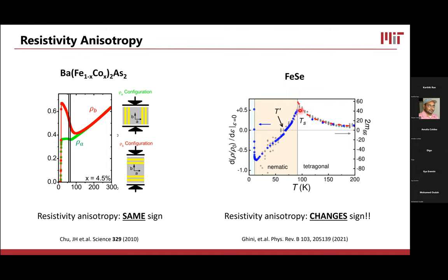But then it does something very strange once you cool below the nematic transition. It has an initial positive value, and then it decreases with cooling. And somewhere about halfway towards zero Kelvin, it actually flips sign. So it goes from having a positive value of the elastoresistivity to a negative value. This paper is from Coldea's group. And if they get very close to zero, they seem to see it flip sign again. I don't really know what's going on there, but it's a very complicated picture. And that complication should be a sign that something more complicated is happening here than in the pnictides.